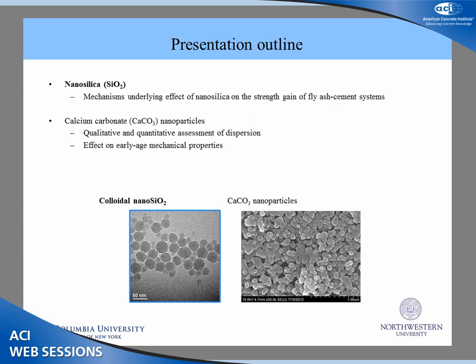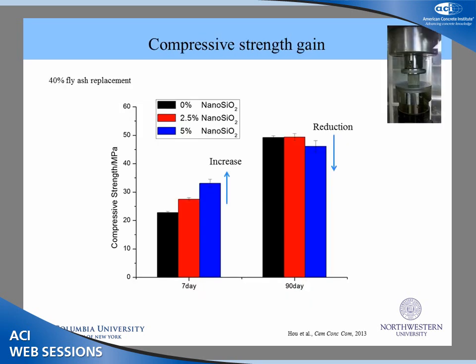So in this talk, we explored two types of nanomaterials, and that's nanosilica and calcium carbonate. So I'm going to go through each of these. And with nanosilica, there's been a lot of work on this particular type. But in this study, we focused on the mechanisms that underlie the effect that nanosilica has on the strength gain of fly ash cement systems. And then with calcium carbonate, the focus was really on dispersion. Dispersion is a very critical issue when using nanomaterials, so there we really focused on the qualitative and quantitative assessment of dispersion, and then the subsequent effect on the early age mechanical properties. So first, nanosilica.